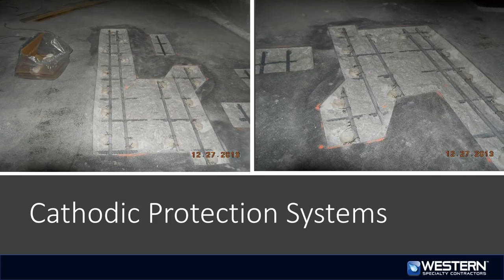Concrete is designed for compressive strengths. It has very high compressive strengths, but it has very low tensile strength. So when your reinforcing steel corrodes and expands, it's basically blowing that concrete up, and that's what causes the spalling to take place. So the zinc anodes are a way to help offset that corrosion of the reinforcing steel. There's various forms of doing the cathodic protection. You've got the disc, sometimes there's the dowels where you can drill and drop it down in a hole. There's other zinc plates that can be mounted and then wired to the structural system. So there's a number of different ways of going about doing that.